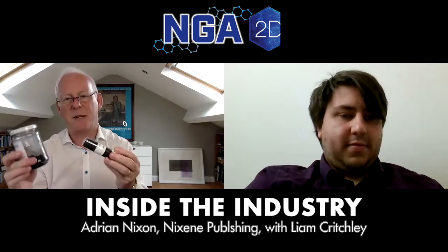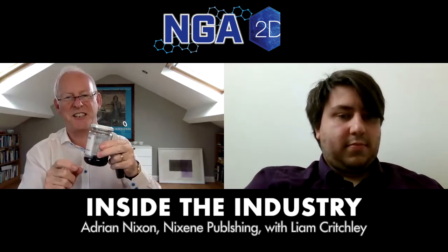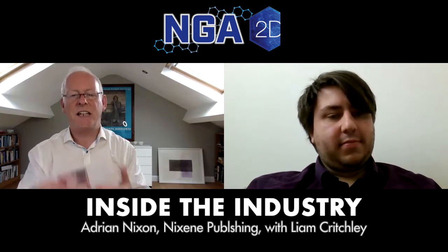Neither of those would make a space elevator tether because they're little bits of graphene. Although it's 200 times stronger than steel, none of the little bits are connected up together. You can make polymer composites with this, but even that isn't strong enough. They would probably make Kevlar stronger, but still not strong enough. So you would need continuous sheet graphene.